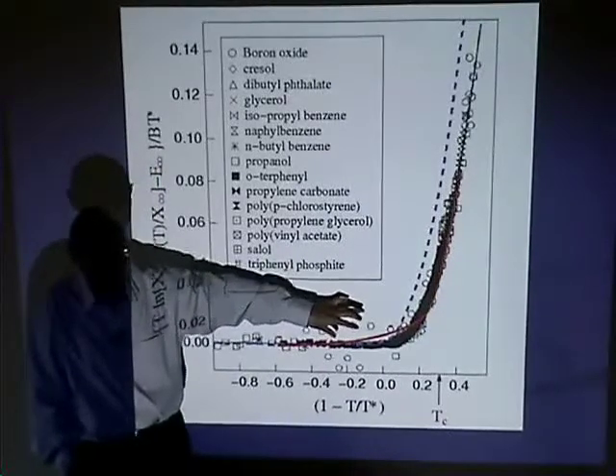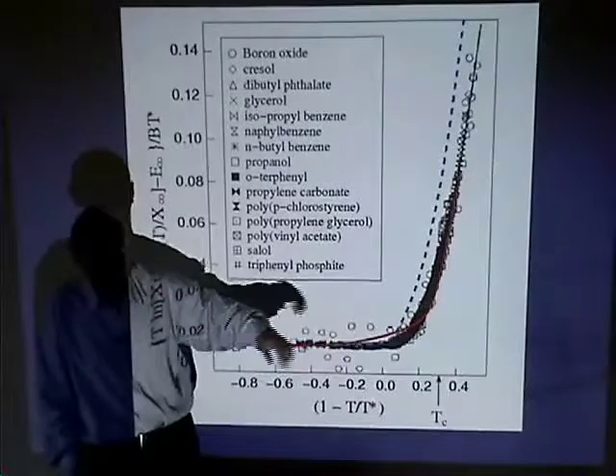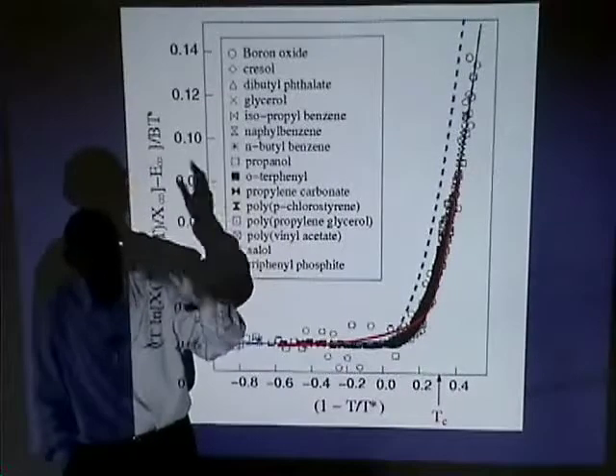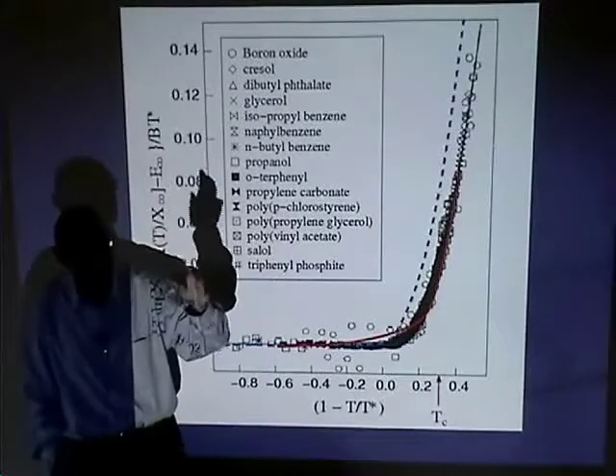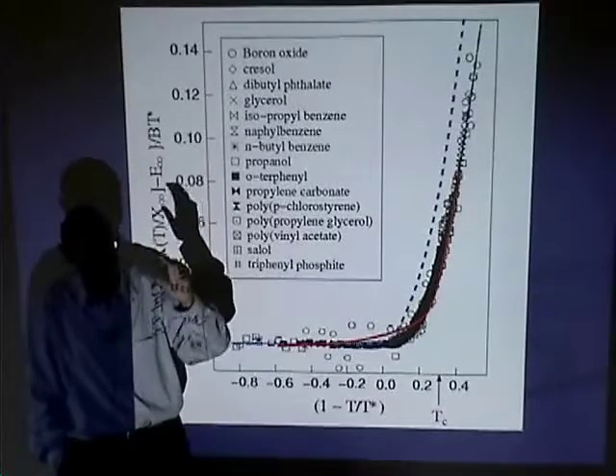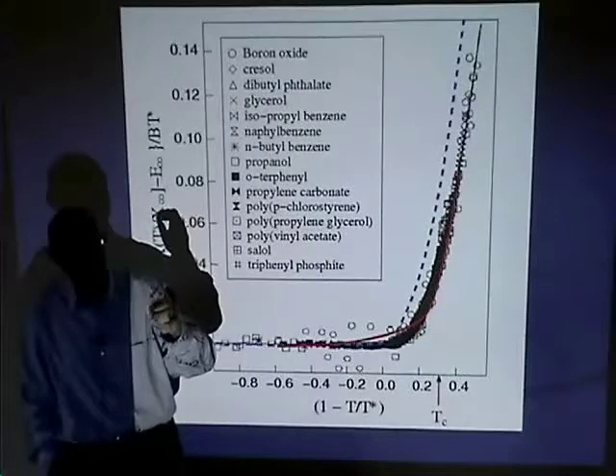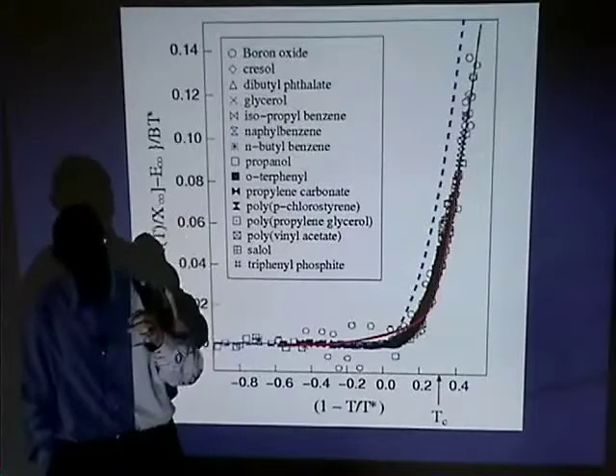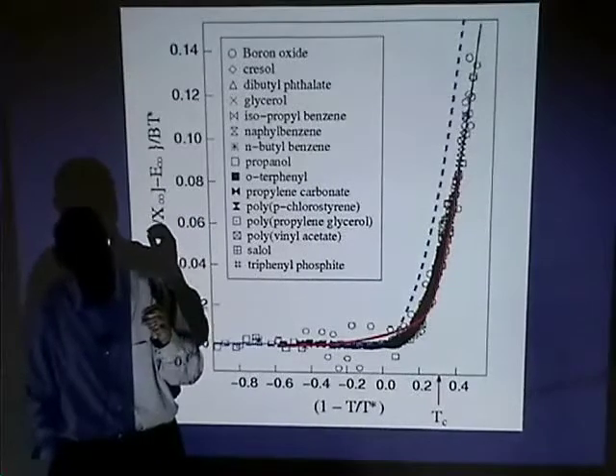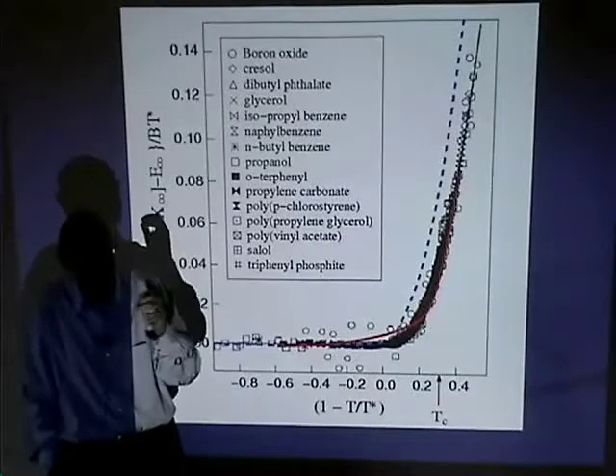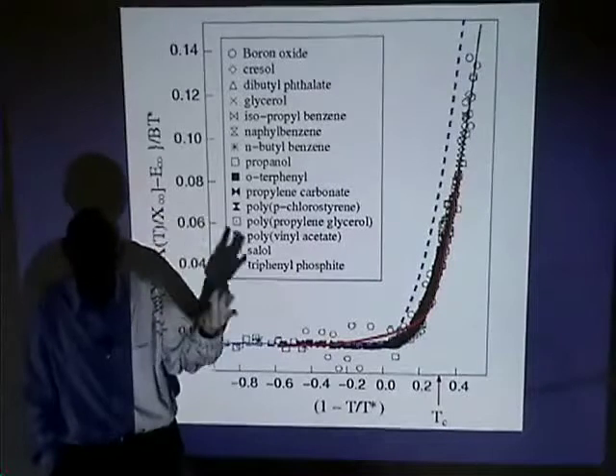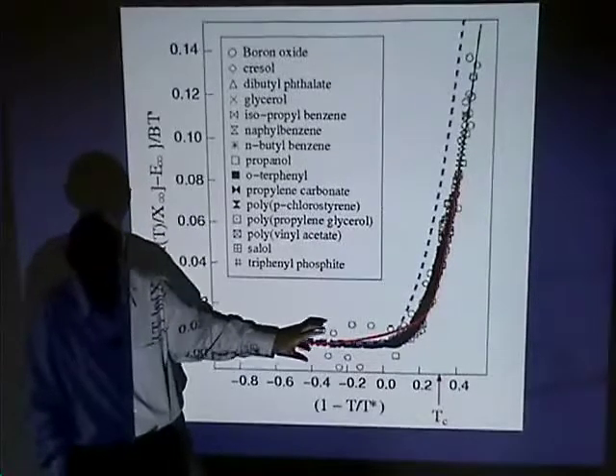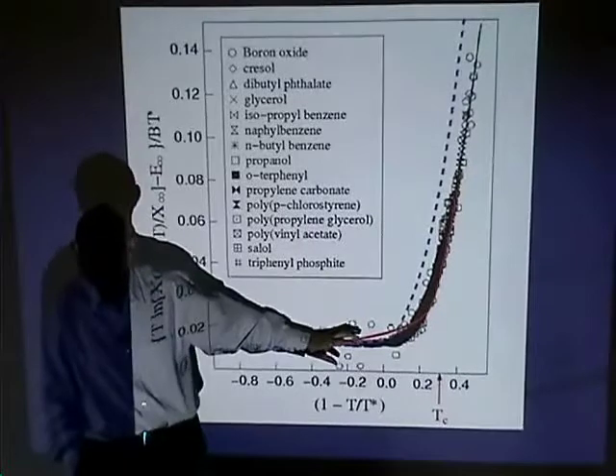And it has come about because we're able to just calculate away. We don't make any assumptions that there should be such a temperature. We basically trust what the simulation gives us in terms of transition state pathways, and there's a lot of sampling, a lot of coarse graining there. It's not just one single process that controls this. So this is the end result of a lot of coarse graining and averaging.